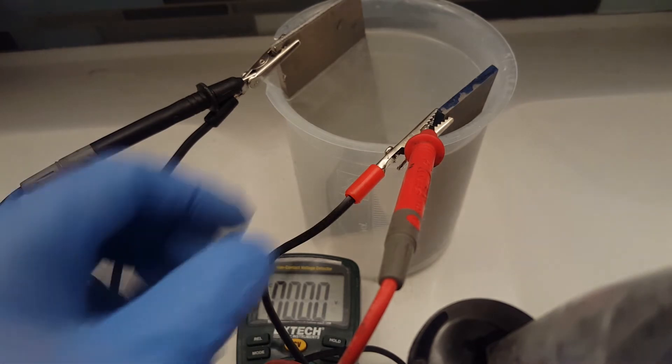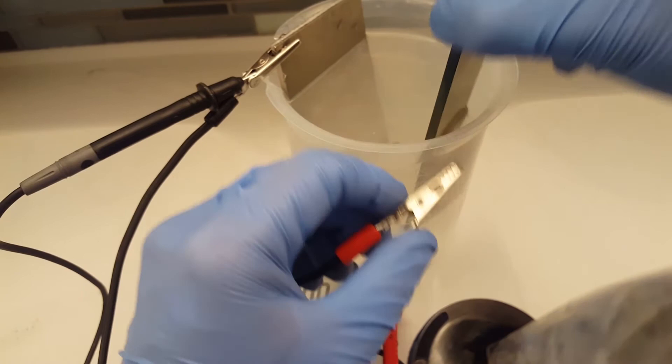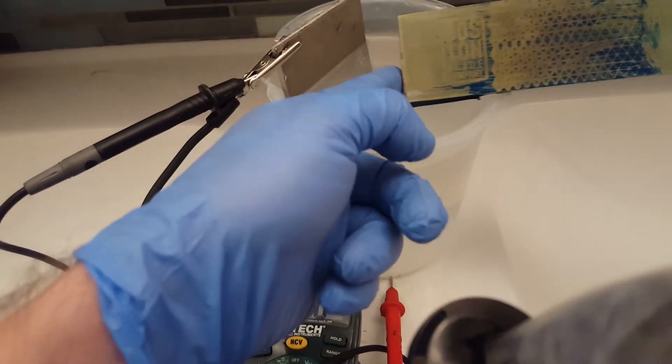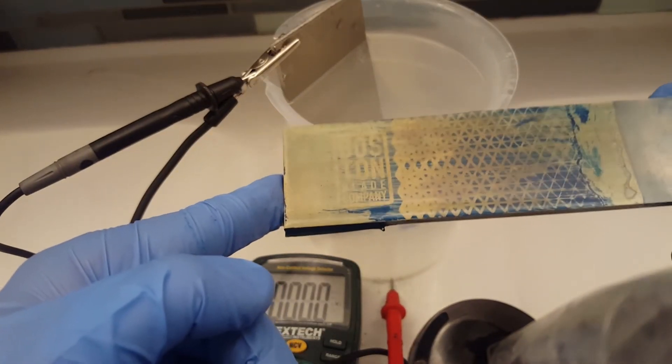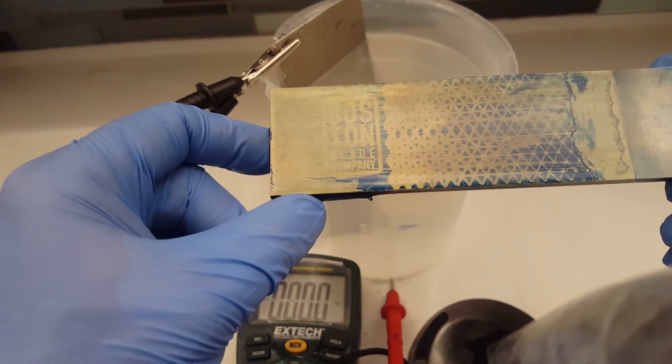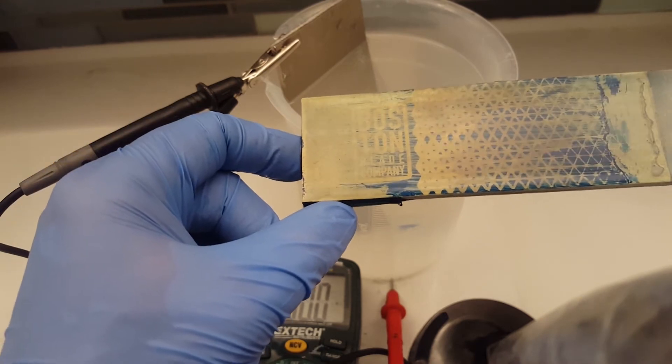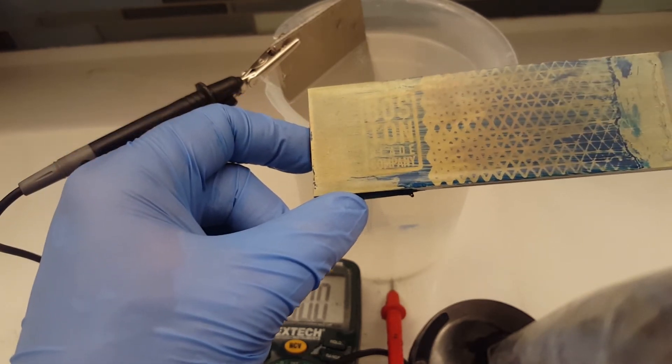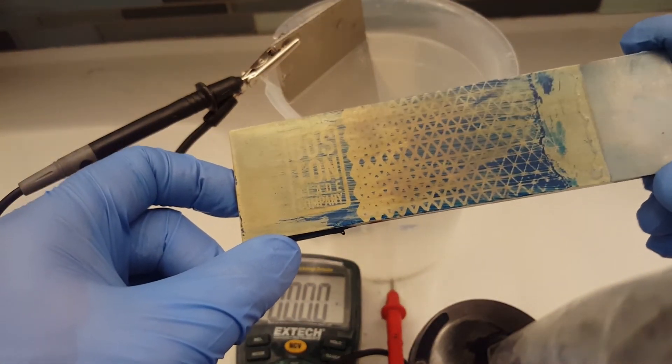We are clear. Let's take a look. Oh yeah, look at that. Not bad. Pretty golden. You can see in some spots there's a little bit more bronze to it. That's where some of our cleaning and things were uneven. This is a test piece so I wasn't worried about that too much. I think I'm going to leave that as is. We're going to clean off the mask, and it should still be blue under there.